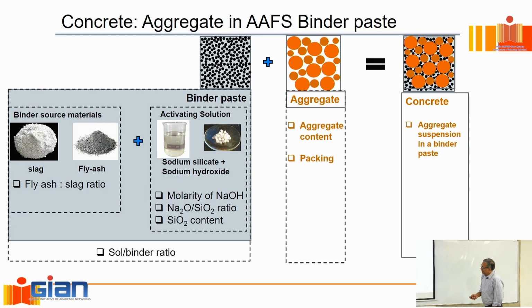But this binder here is much, much more complicated. It is not as straightforward as what we did with cement paste. Why? Because if you look at cement paste, what are the variables that I have? There's fundamentally only one variable, the water to cement ratio. Here, it is not limited to that. The binder source material itself could be a combination of slag and fly ash, where I could have 100% slag or 100% fly ash, or a combination of these two. So that's the first variable.